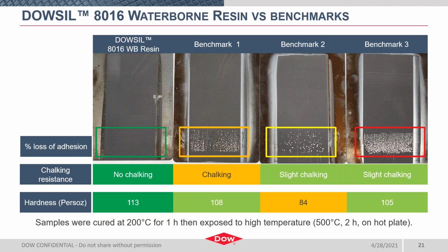For consistency, all coating samples here were drawn down on cold rolled steel, cured for an hour at 200C, and the formulation components and parameters were also held constant, which includes that pigment to binder and pigment to silica ratio. The only variable here is going to be that binder type or binder composition. The high temperature resistance was then assessed of the 8016 in these three benchmark products by measuring adhesion, chalking resistance, and pendulum hardness. Among all of these products, the DOWSIL 8016 did exhibit the best overall performance.